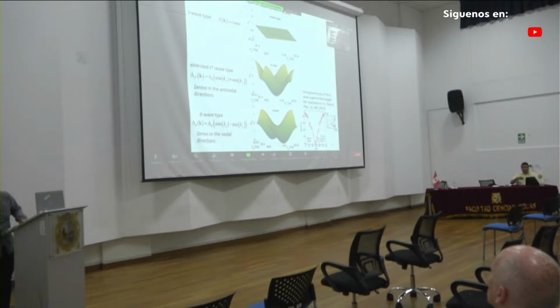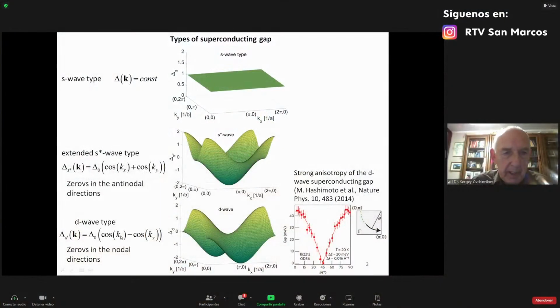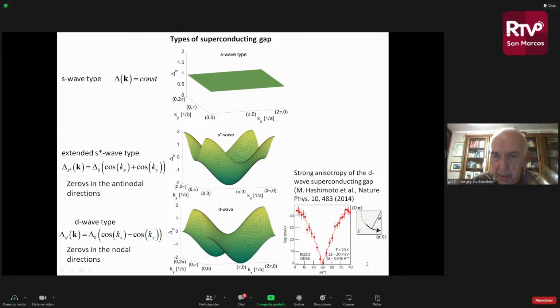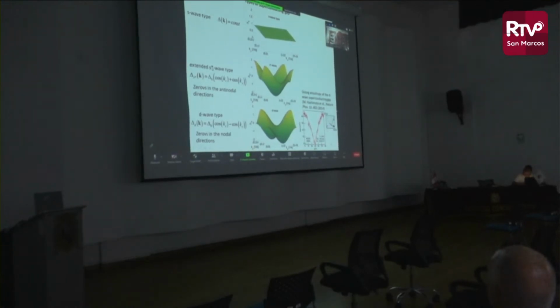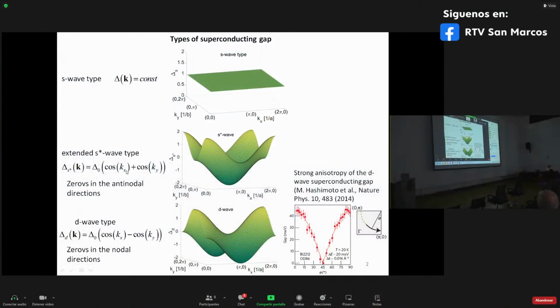Different symmetries of the superconductor gap. The upper one is the S-wave. It doesn't depend on the wave number at all. The lower one is the very well known D-wave, where the gap is determined by the nodal direction in the Brillouin zone. Nevertheless, extended S-wave, S-star wave symmetry is also possible. That is given by the sum of cosines, cos kx and cos ky.